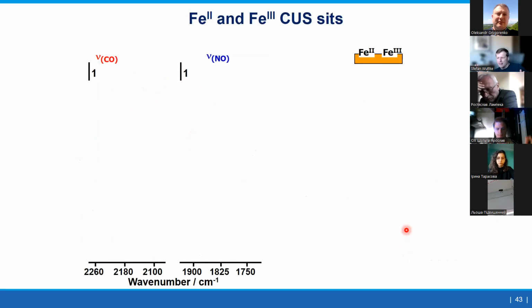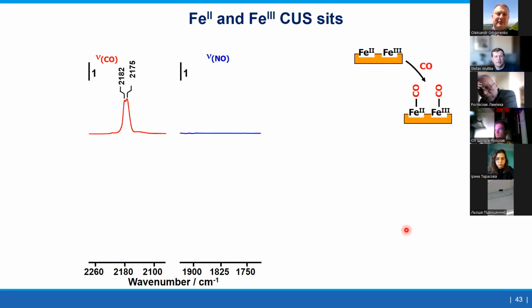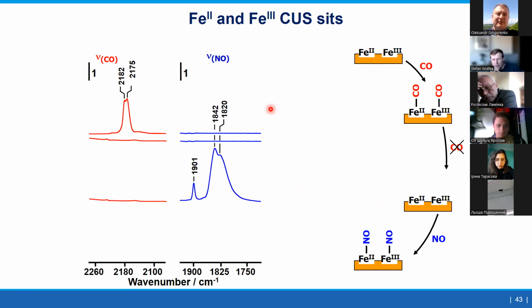So we have a material with 2 undercoordinated sites, iron 2+ and iron 3+. This we know already from normal in situ characterization. We characterize, we know the bands, and now we're doing the flow. And we study when we put CO, we have 2 undercoordinated sites, so iron 2+ and iron 3+. So we see the species, we understand, then we remove CO just by argon stream. Then we put NO on it. There we have different species.